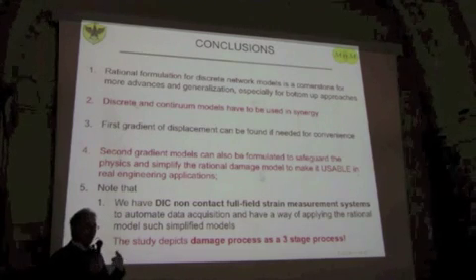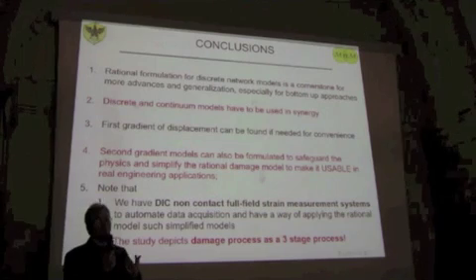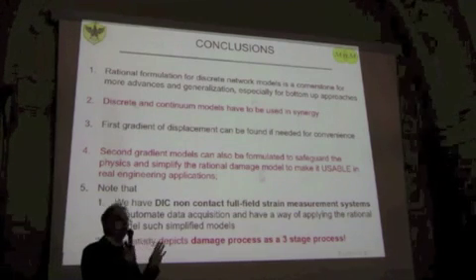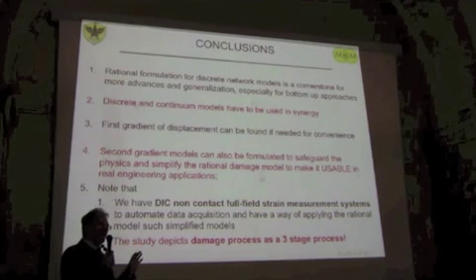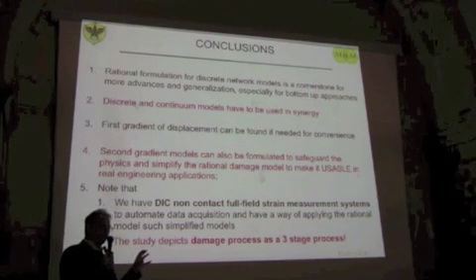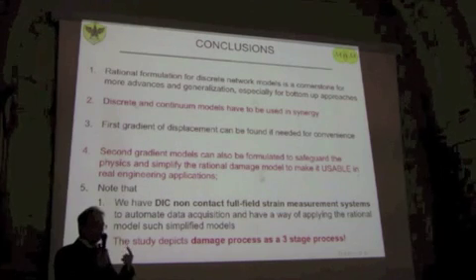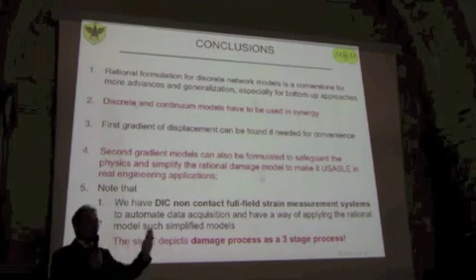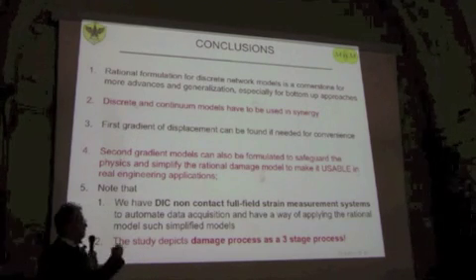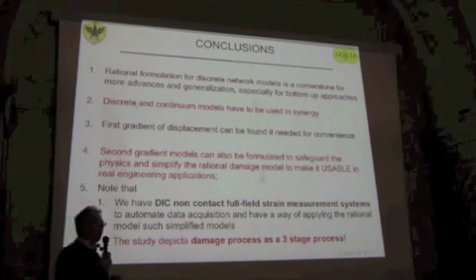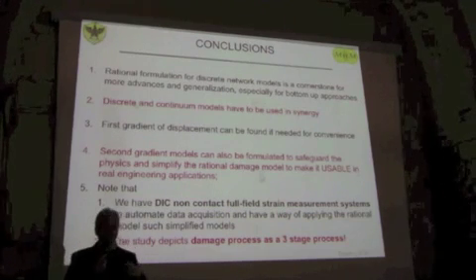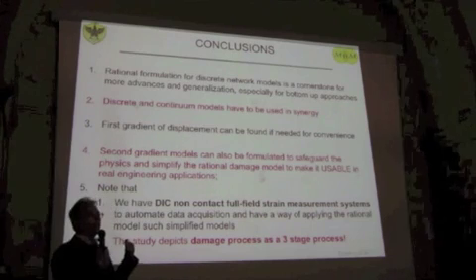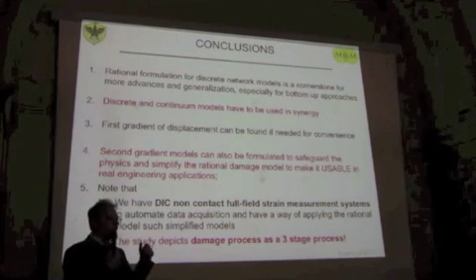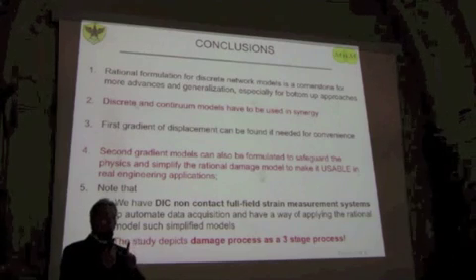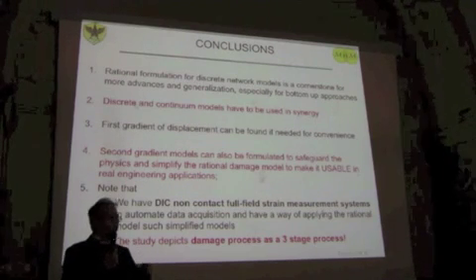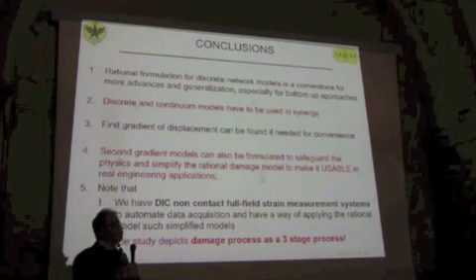The other thing is this. Through this exercise, I have realized now that the damage problem is not really a two-stage process. It's not really nucleation and propagation. But it's more like nucleation in a dilute regime, nucleation in a cross-talking regime, but still homogeneous over the entire lattice domain, and then there is the propagation. And this is of practical importance, because if you are worrying about early warnings in these catastrophic sensitive systems, this is very key, so that we know where we should go and check for critical warning signal. Sorry for having been a little bit long.